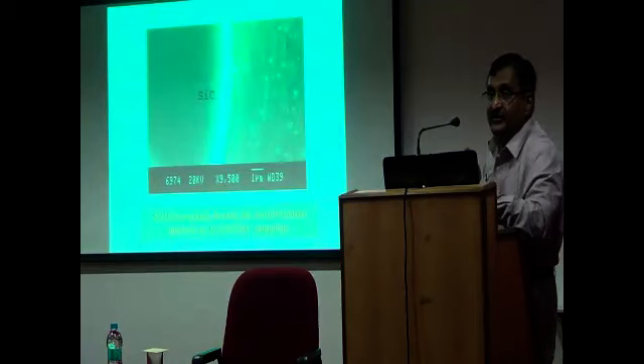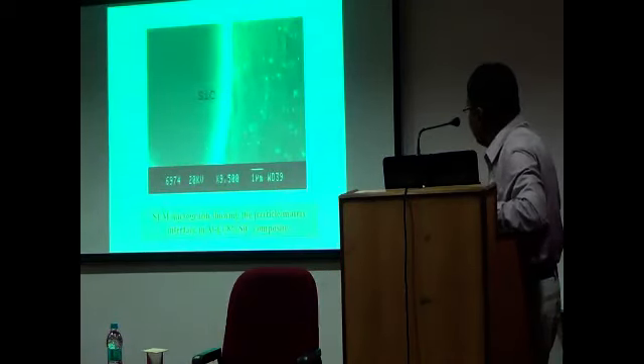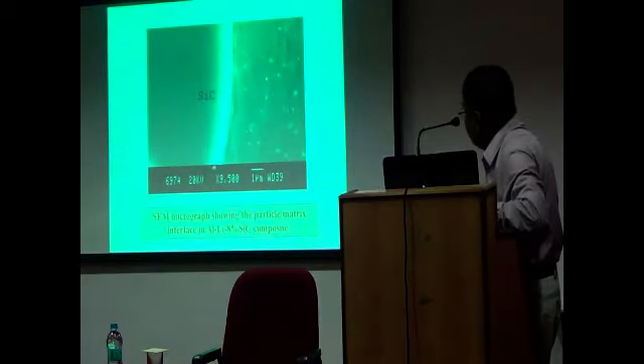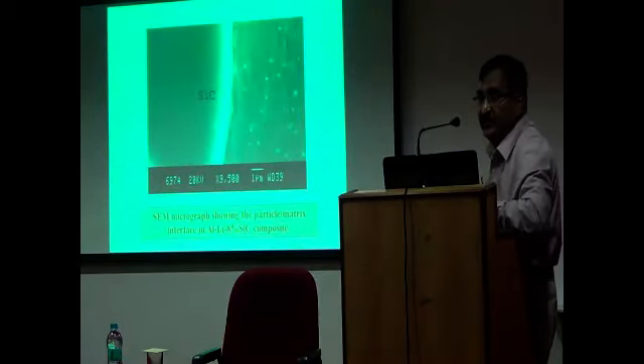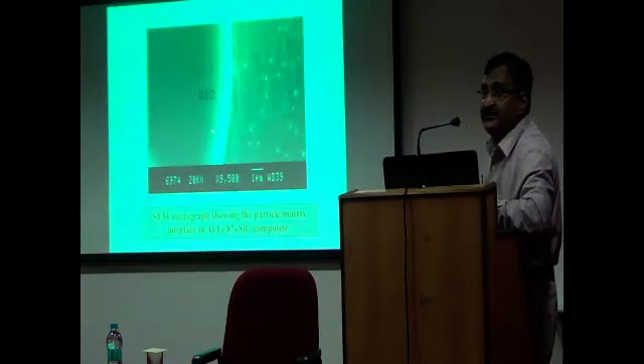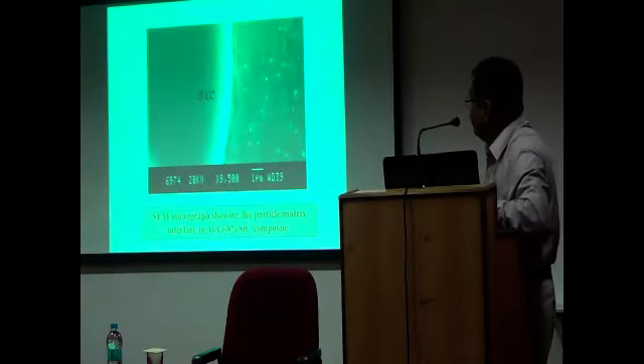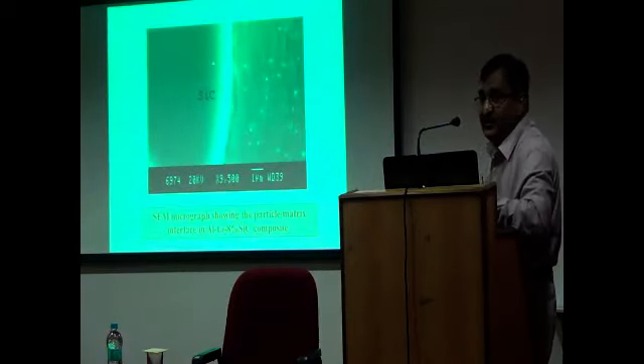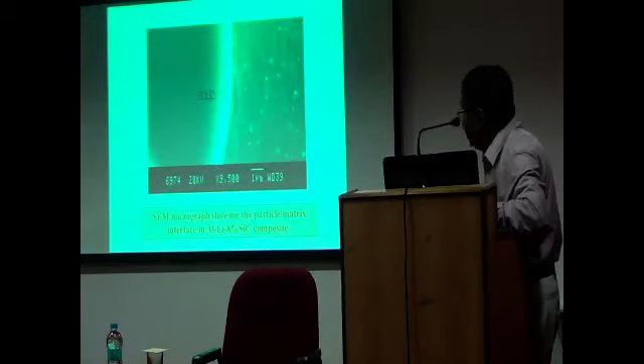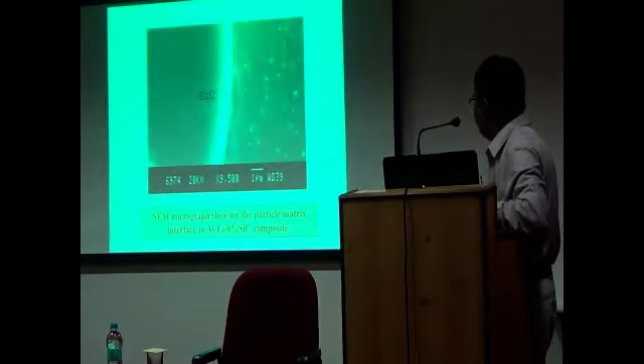And this is the interface. I mentioned the interface, the boundary between the particle and the matrix. This is the particle, this is the aluminum matrix. You need a very clean interface. There should not be any reaction product. If there is any reaction, it will deteriorate the properties. So we need to choose the processing conditions to maintain a very clean interface.